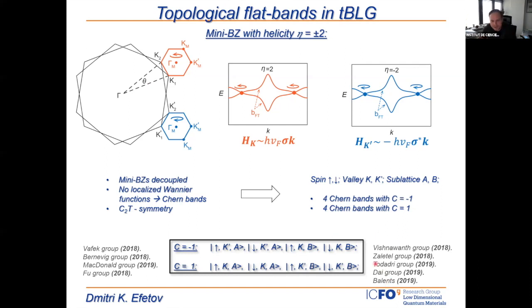However, in graphene, one can play tricks. One can try to induce gaps and gap out these different Chern bands. For this, one needs to break C2T symmetry one way or the other. For example, the groups of David Goldhaber-Gordon and Andrea Young broke C2 symmetry by aligning graphene to hBN. The hBN substrate breaks the inversion symmetry on a single particle level. One can also try to break time reversal by applying magnetic fields. And another possibility is that interactions break those symmetries by themselves. I will talk along the lines of interaction-broken C2T symmetry.